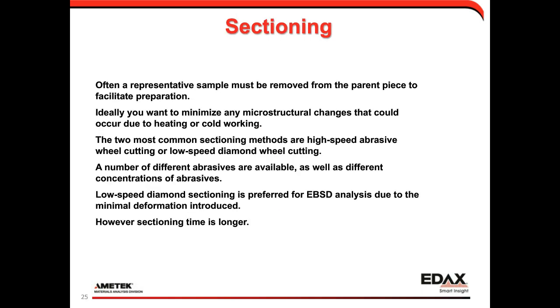So the first step is to section a sample. Usually you start with a larger piece of material, and you're going to section it down into something that's going to fit nicely into an SEM. With EBSD, of course, we have to tilt the sample to around 70 degrees, so we generally use smaller pieces, and sometimes you look at flat.